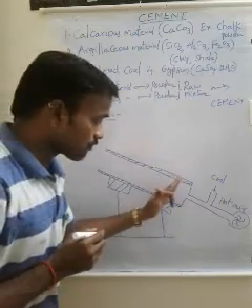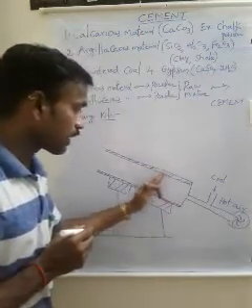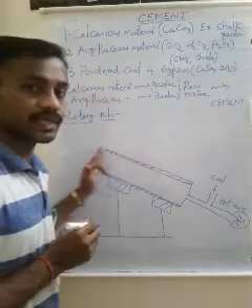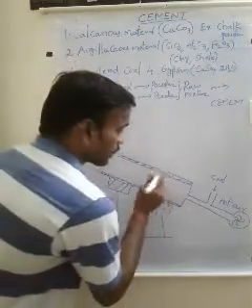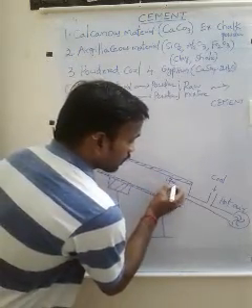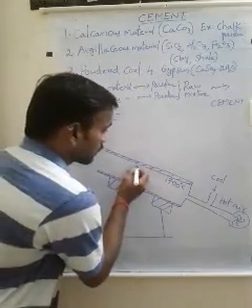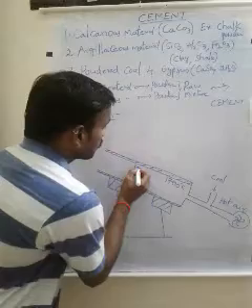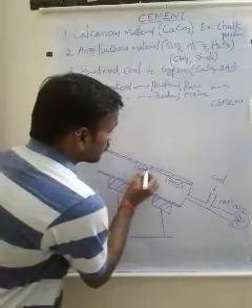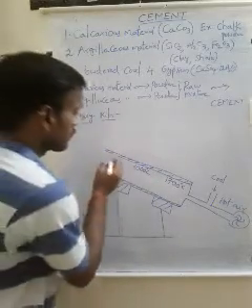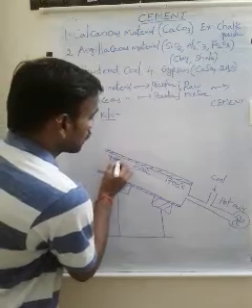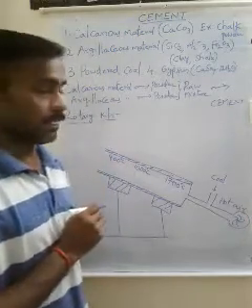From lower end to higher end, temperature decreases. In the lower part of the kiln, temperature is around 1700 degrees centigrade. In the central part, around 1000 degrees centigrade. At the top of the kiln, around 400 degrees centigrade.